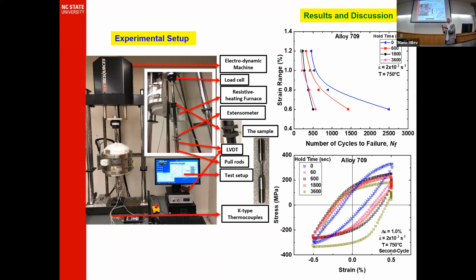So the results from what we studied, the effect of temperature, strain, and hold time, show that the number of cycles to failure, or the creep fatigue life of alloy 709, decreases when we increase the temperature. It decreases when we increase the strain or the fatigue, and decreases when we increase hold time or the creep damage. So this all affects the material life itself.